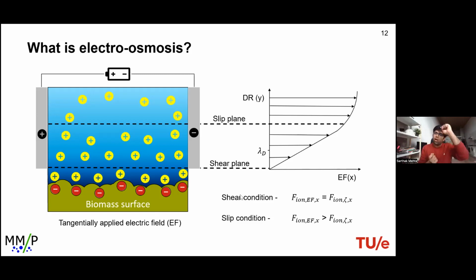But as you go along the y-axis, the net potential experienced by the ions in the diffusive region reduces because of the exponential decay. At some point, referred to as the slip plane in the y-axis, the electric field force is sufficient to overcome this attractive force between biomass and ions, leading to the slipping of these ions and an electro-osmotic flow.